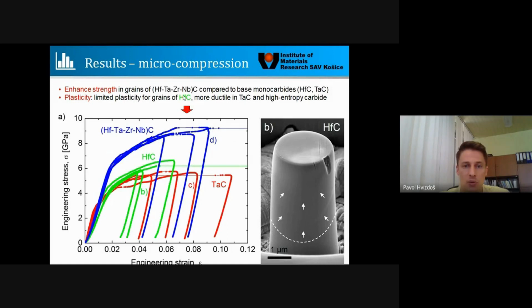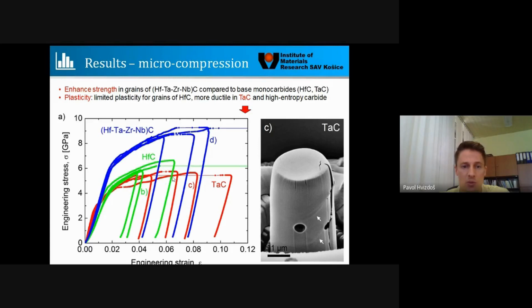We compressed first the hafnium carbide samples, as you can see in green. They deformed to a specific level and then they broke. You can see also fractures. On the top there are some lines, which is basically the fractured surface due to dislocation activity. Maybe if you have good eyes, you can see on the right side image some ellipsoidal lines. Those are slip patterns on the surface. It's very hard to observe them on hafnium carbide before the final failure occurs. But if we check tantalum carbide, which was able to deform much farther, so its deformability was a little bit better than hafnium carbide, we could see the slip lines on the side much better. Okay, one can argue that we also have pores, and this could have influence on deformability.